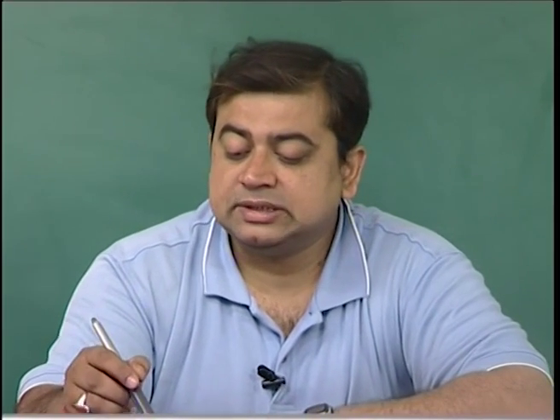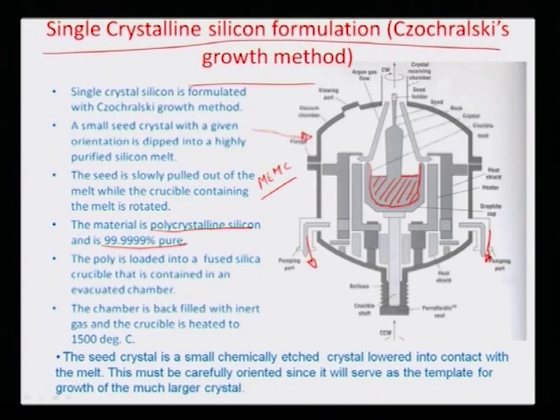So the way the processing goes is that when this crucible is rotated, there is something called a seed crystal, which has been obtained from an earlier process, and the seed can be a very small crystal grown in a certain direction, let's say the [100] direction. So this seed has been grown from an earlier process, it is a pure crystal, and the seed is inserted into this melt somewhere here, as is illustrated here. And so the relative rotation between the seed and the crucible can be varied by varying the relative RPM.